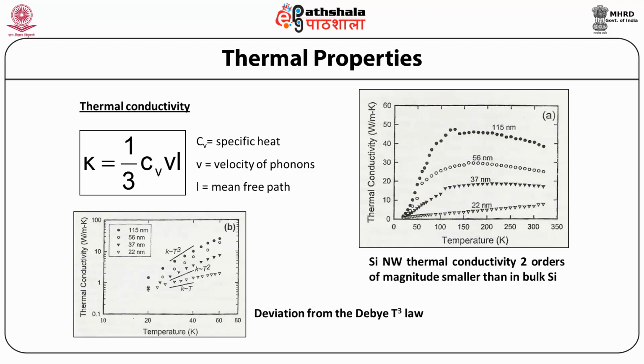The experiments show that the thermal conductivity of a small homogeneous nanowire may be more than one order of magnitude smaller than in the bulk, arising mainly from a strong boundary scattering effect. Phonon confinement effect may eventually become important in still smaller diameter nanowire.